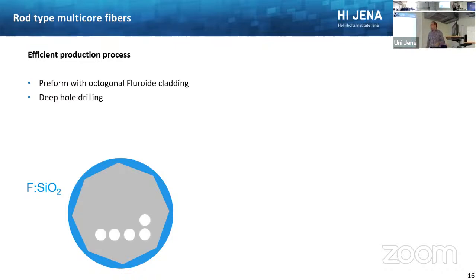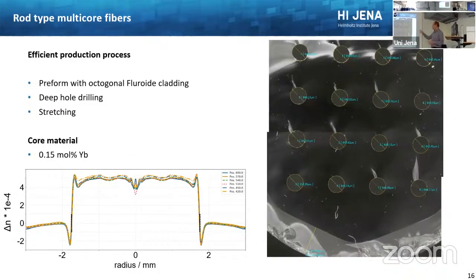And what you then basically do is you drill holes into this structure. You do deep hole drilling. This is possible, certain companies can do that. Drill these holes in, and then you have basically a preform that's shown on the right side here. You can stretch it out a bit, and at the end have this preform. You can see it on the right side with holes that have a diameter of about 600 microns.